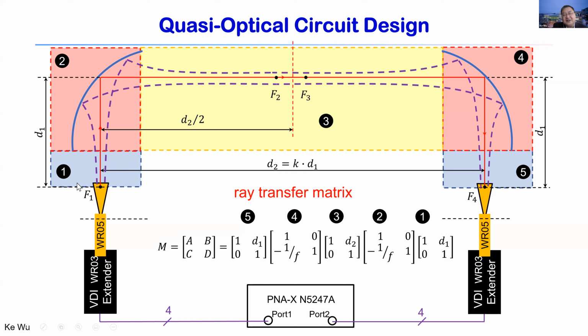First of all, from horn port to horn port, you need to have a very good stable optic path over the broadband frequency range, which means a frequency independent optic path. This is one of the first important things you have to pay attention to regarding the measurement setup. Second, you need to develop corrugated horns which allow you to have a very smooth beam waist variation as the frequency changes, which means it's like elastic. So in this case, it becomes frequency independent. The total path from port to port measurements becomes frequency independent, which means the optic path becomes frequency independent. Let's say it this way.